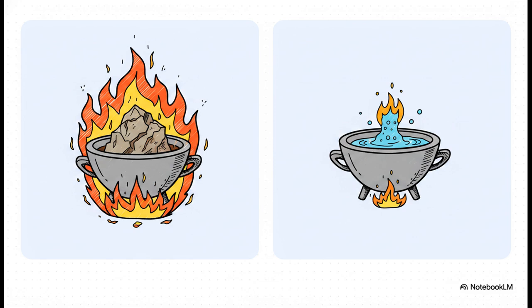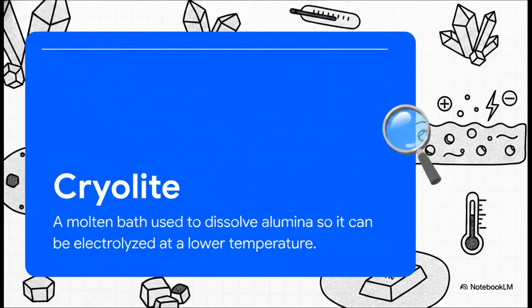But then, chemists found a real game changer, a clever solvent that drastically lowered the required temperature, dropping the melting point by a massive 1,000 degrees. That magic solvent? It's called cryolite. By dissolving about 13% of the produced alumina in a bath of molten cryolite, and then throwing a bit of aluminum fluoride into the mix, the solution actually becomes an electrically conductive liquid at a much more manageable 1273 Kelvin. This single chemical workaround is literally the secret sauce that makes modern commercial aluminum production physically and economically possible.